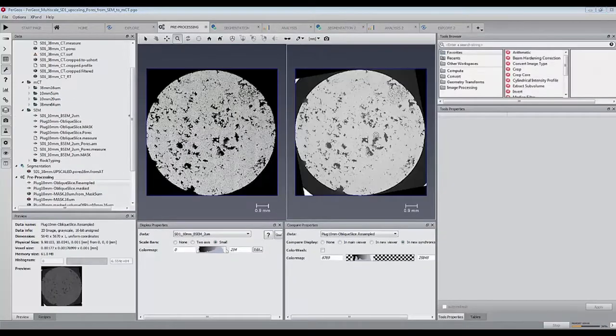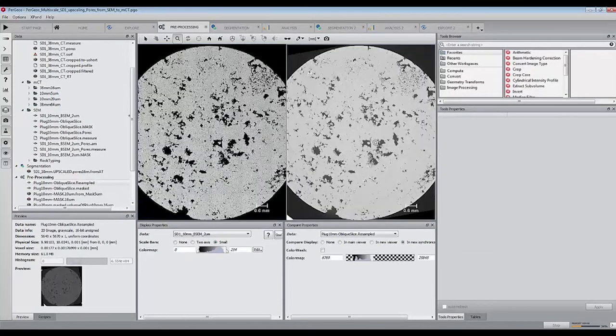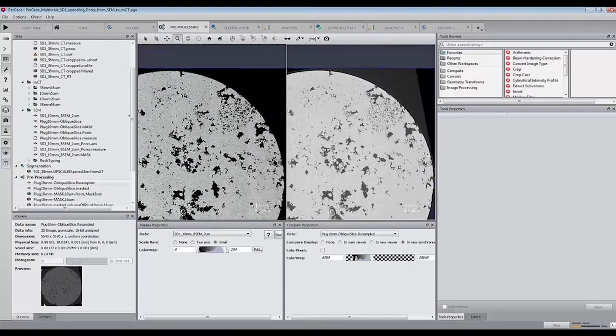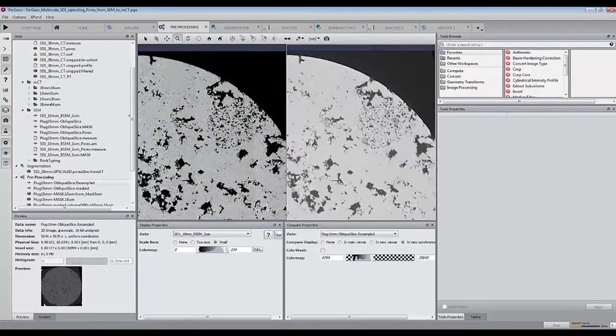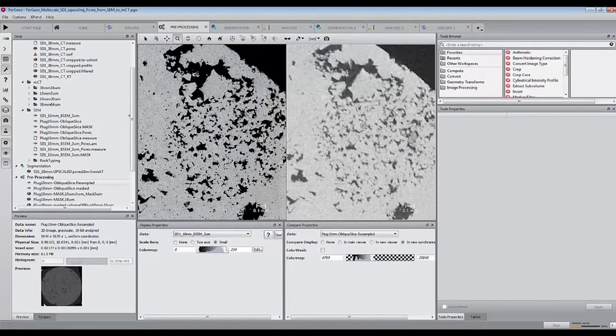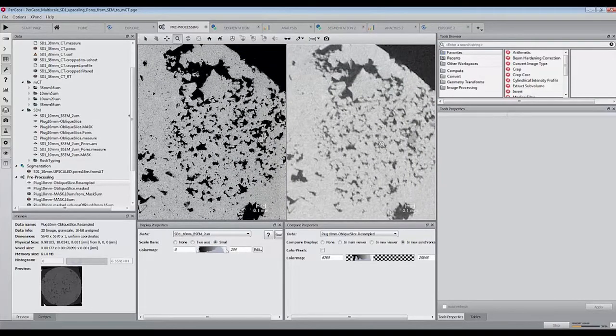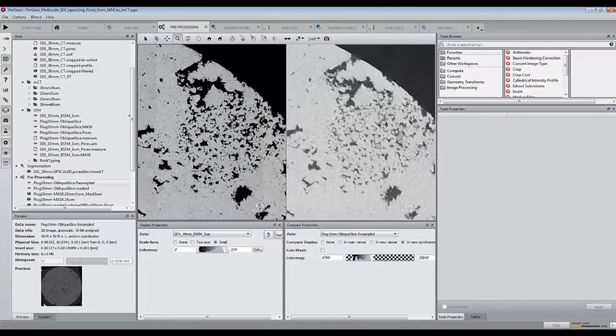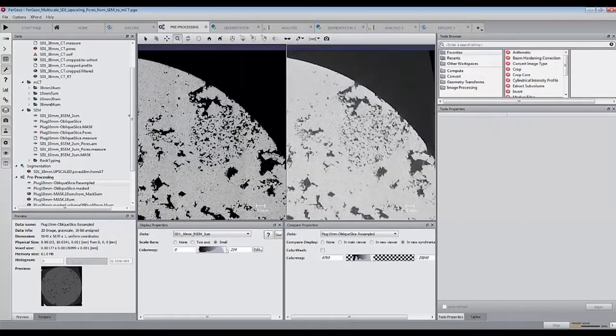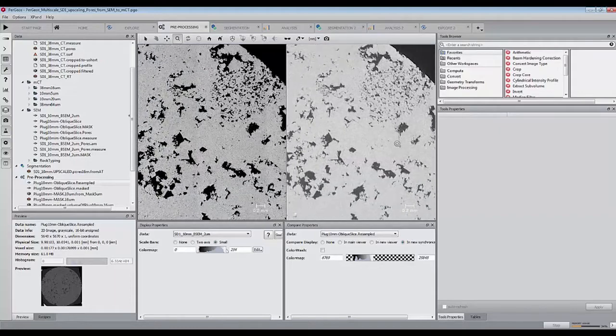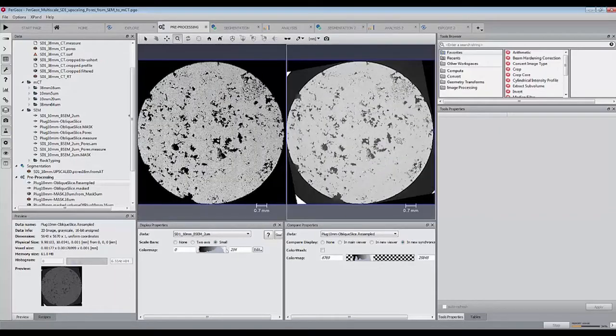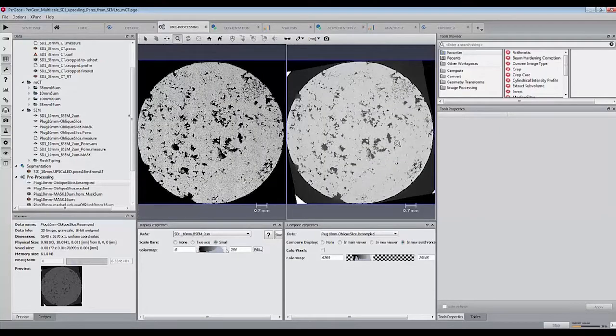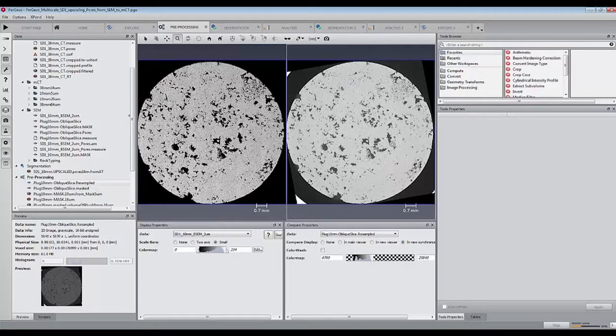Looking at the 5 micron microCT slice and comparing with the SEM 2 micron slice, we clearly see that some pores are not resolved at 5 microns. The porosity is around 7% when it should be 10.36%.